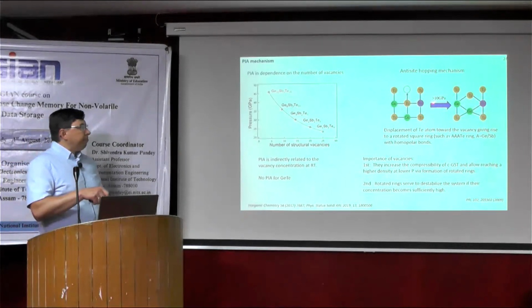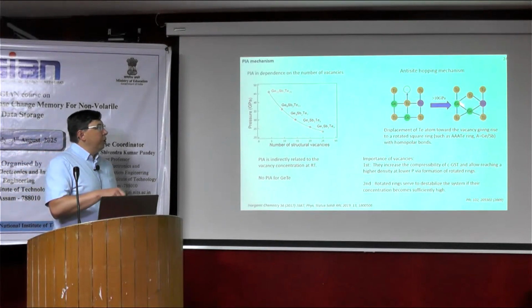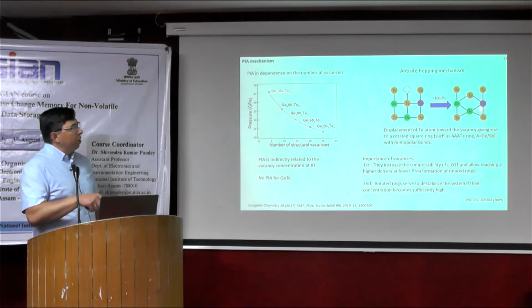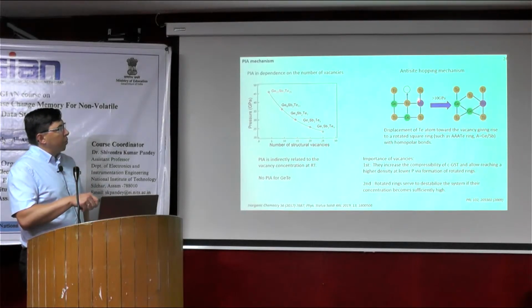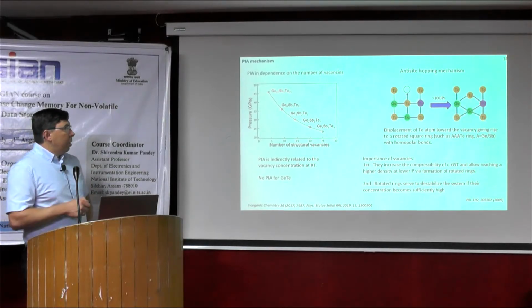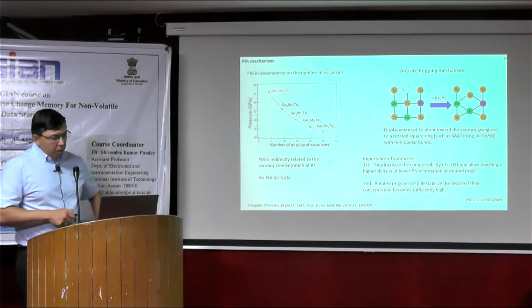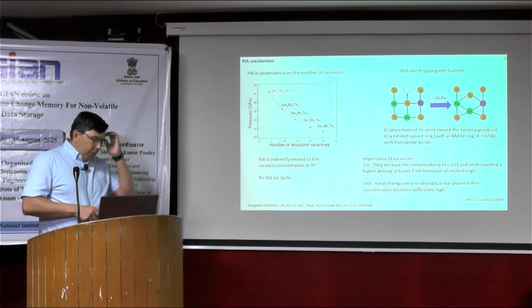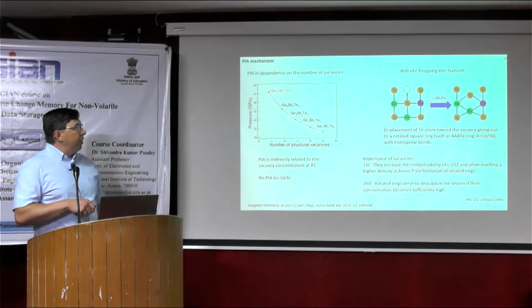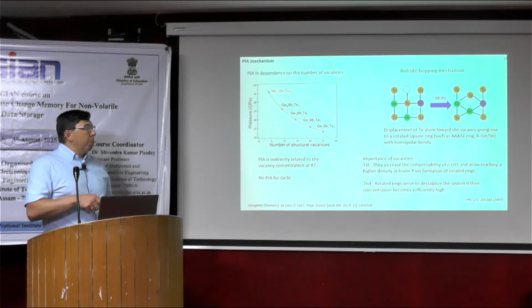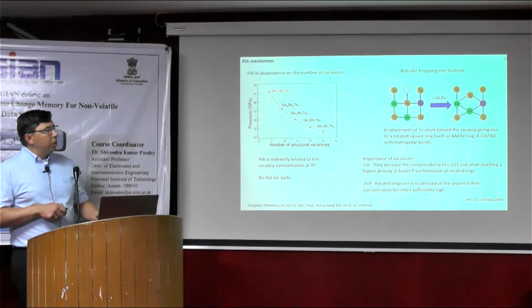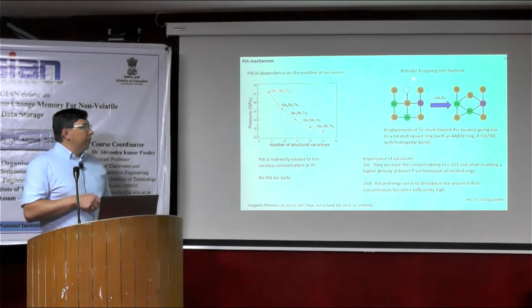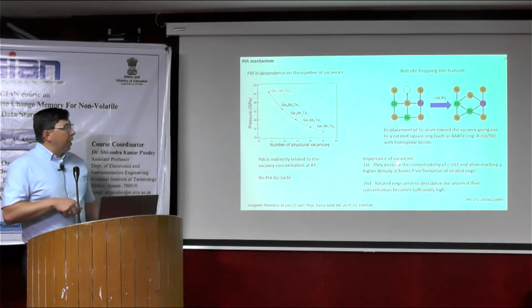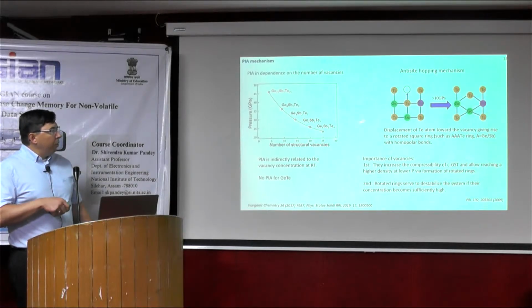And then we have a formation of new bonds here, like homopolar bonds: germanium-germanium, then germanium-antimony, and others. Here we do not have it because tellurium was sitting here. So there are two important roles of vacancies in this system. First, the vacancies increase the compressibility of the cubic GST and allow reaching a high density of the phase.